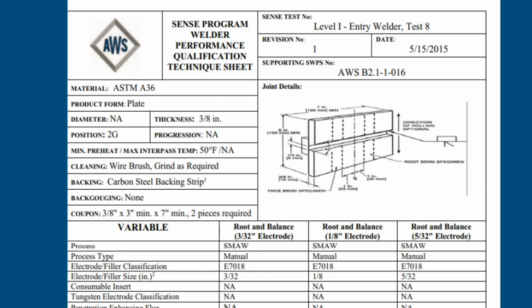And this is a welder performance qualification technique sheet, which is kind of wordy, but it's a variation of a WPS, a welding procedure specification, if you're familiar with that. It's going to give basic variables that the welder can use. So we're going to weld this on 3/8 thickness. It has to be ASTM A36 plate. If you're not familiar with your different grades of material, you can certainly look that up, but it's your common structural welding material. If you call up your supplier and ask them for a piece of angle iron or a piece of flat stock steel, they're probably going to give you A36. But specify, if you're doing bend tests, specify so you make sure. Position 2G.